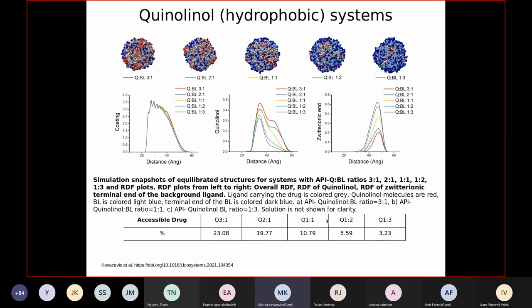We wanted to see to what extent the drug is covered beneath the surface, and as we can see from the table, the percentage which is available to the solvent is quite low. So, it goes up to 20%, and it would be difficult to increase this percentage more, because we could compromise the solubility of the entire systems.